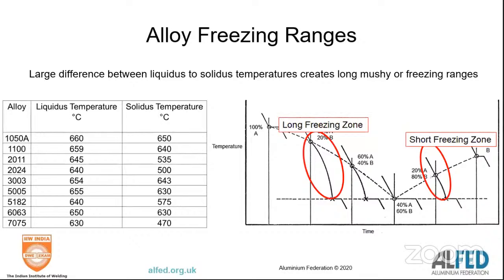One of the problems you have with aluminium is the big temperature gap from the solidus temperature, when the alloy mix starts to solidify, to the eutectic temperature. And if you drop down to 7075, and the 7000 series are regarded as very difficult to weld, pure alloy would melt at 630 degrees, but the eutectic is 470 degrees. That means that you've got a very large freezing zone, and that freezing zone will be subjected to various expansion contraction forces which will pull it apart. So if you have a very large freezing zone, the alloy becomes very, very difficult to weld.